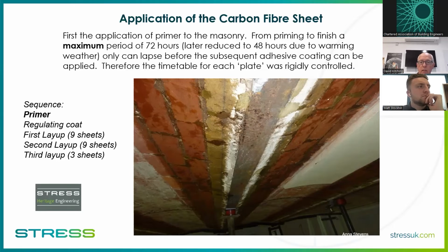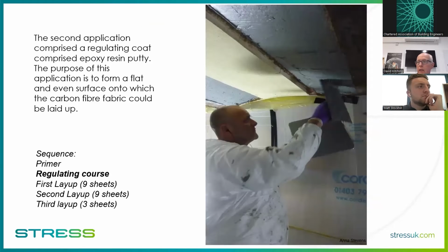So you prime that surface, and then you actually put up a regulating course. Now, for those of you who have tried plastering, you know how difficult it is. This is epoxy putty or epoxy mortar. It's about 15 times, if not 20 times, harder to apply. It sticks fine, but to smooth it out, to get a really good smooth surface, particularly curved, is not easy. John here has worked for us for about 25 years as a master plasterer and master screeder. He made it look easy. So there we go. We've now got this nice smooth surface which we can adhere the carbon fibre to.